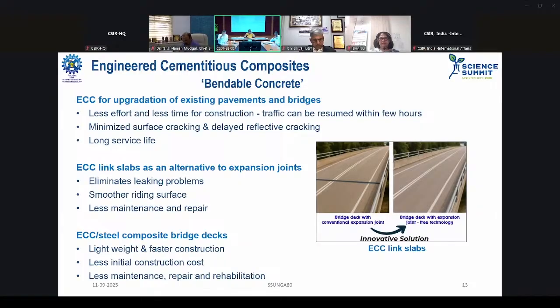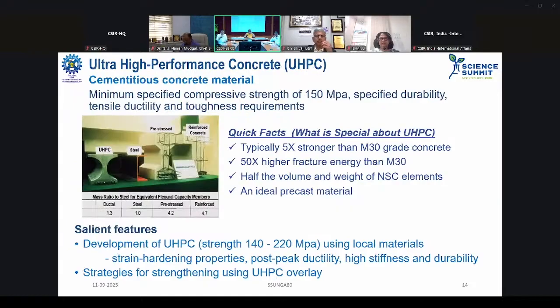And even ECC steel composite bridge decks, which can have very lightweight construction and faster construction with a very low initial construction cost. Another area I've been working on is ultra high performance cement concrete, UHPC, a cementitious material which can have 5 to 6 times more strength than M30 grade concrete. It has about 50 times higher fracture energy and almost half of the weight and volume of normal reinforced concrete, and hence it is very ideal as a precast material.